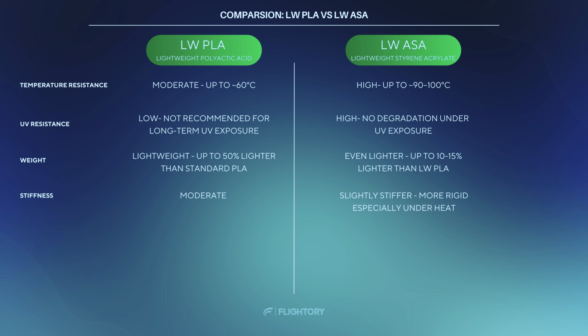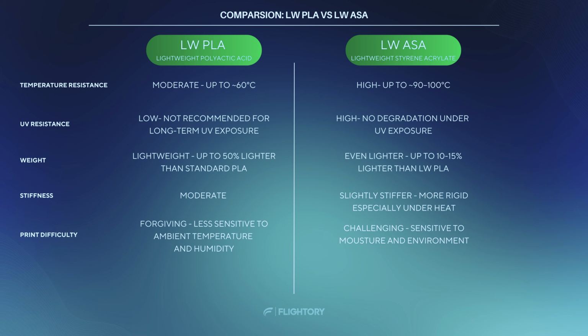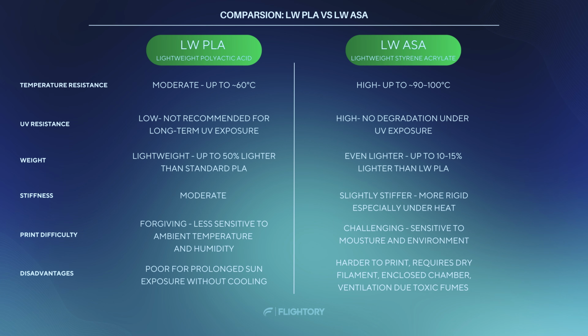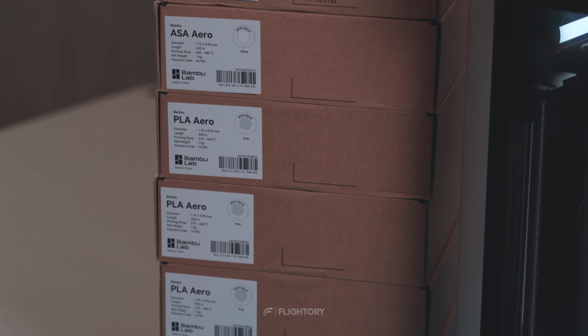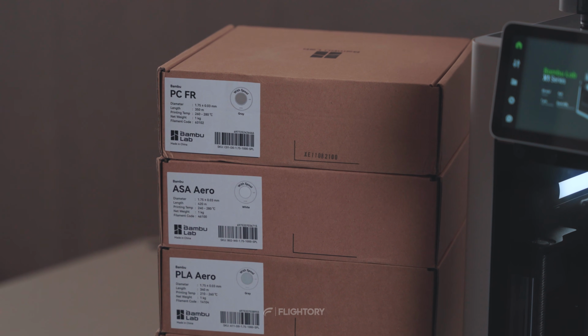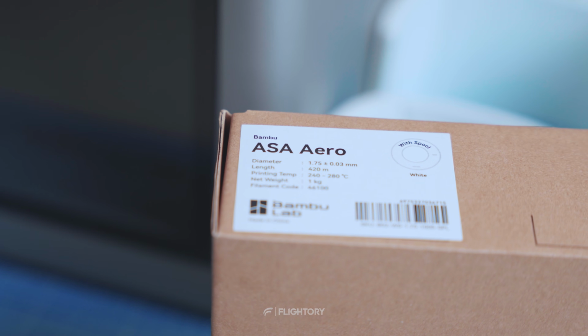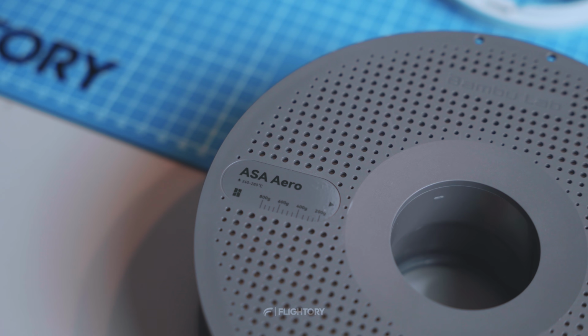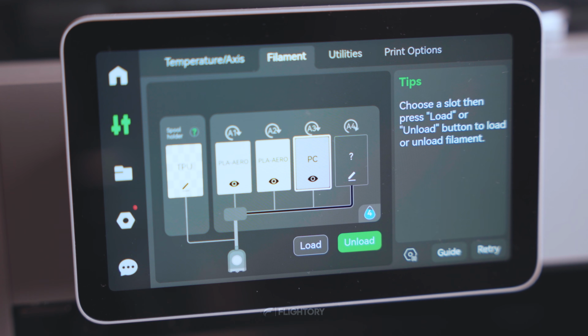The downside is that it's more challenging to print. Proper drying of the filament is essential, along with maintaining a higher and stable ambient temperature. So using a printer with an enclosed chamber like the X1C is highly recommended. Additionally, proper room ventilation is important as this material releases toxic fumes during printing. Bambu Lab also offers its own line of lightweight filaments called PLA Aero and ASA Aero. These are active foaming materials that expand during printing.